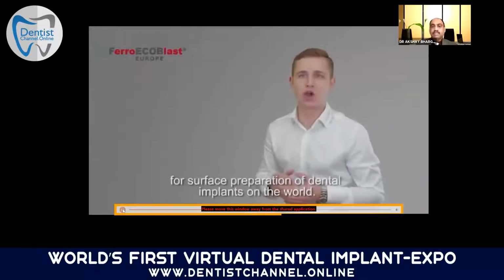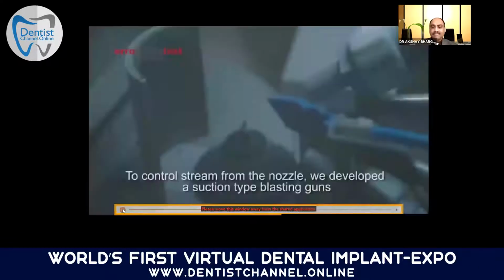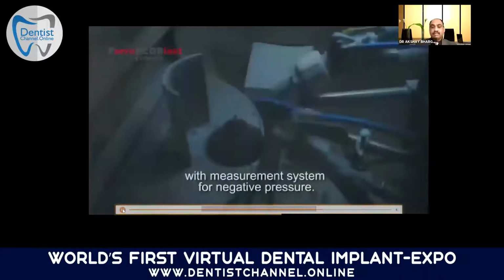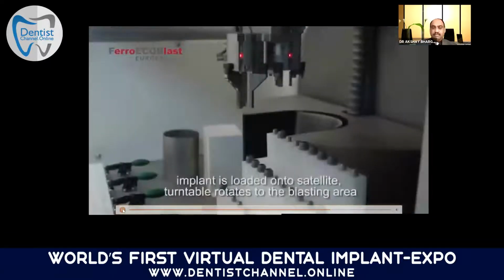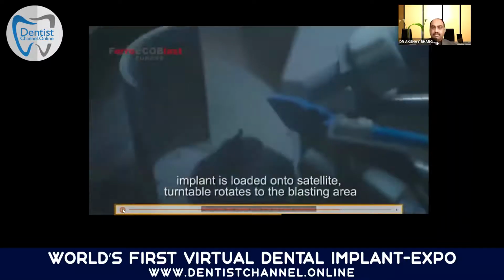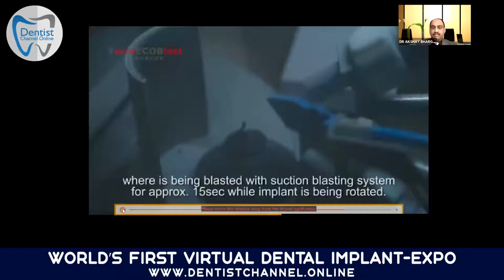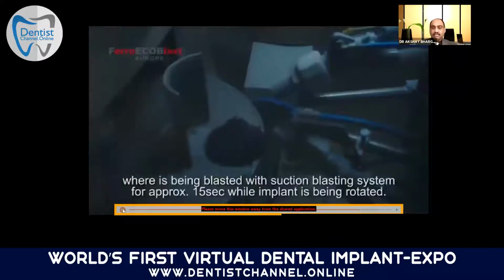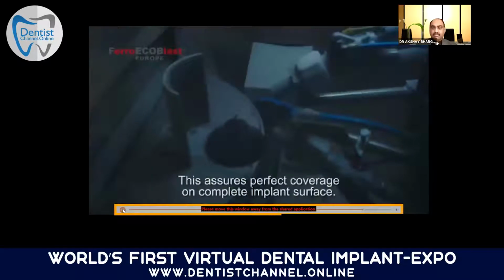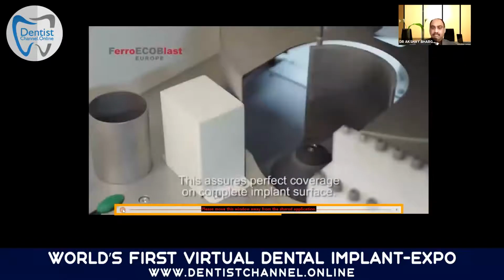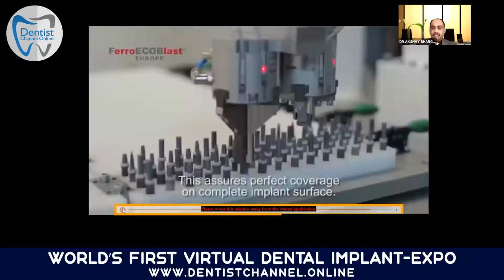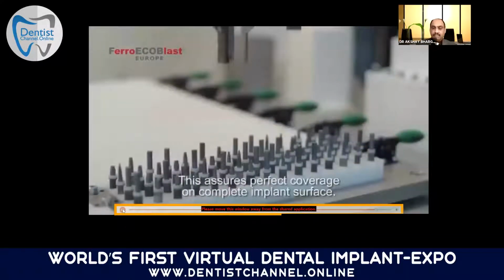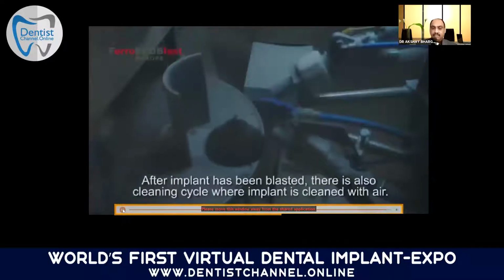To control the stream from the nozzle, we developed suction-type blasting guns with a measurement system for negative pressure. After the implant is loaded onto the satellite, the turntable rotates to the blasting area, where it is blasted with the suction blasting system for approximately 15 seconds while the implant is being rotated. This assures perfect coverage on the complete implant surface. After the implant has been blasted, there's also a cleaning cycle where the implant is cleaned with air.